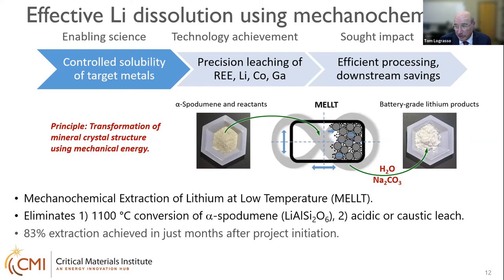Furthermore, the mechanochemical approach not only transforms it to a leachable form, but can also perform the chemistry to convert it directly to either the carbonate or the hydroxide. And so we get rid of the acid and caustic leach steps. So lots of process intensification here. The latest report just this month was that we were achieving 83% extraction of the lithium present, just a few months after we initiated the project. So this is holding lots of potential.